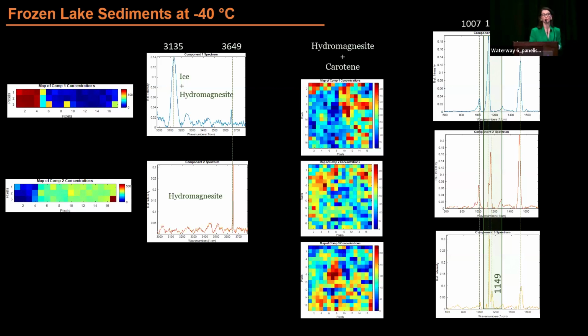And here, this was the first result to test the model with a much more complex organic sample with the hydromagnesite. What we have seen is that the water stretching region is perfectly located, with ice and hydromagnesite aggregated together. In the next slide, the carbonate region is much more complicated. Actually, it's a successful model, because the red dots correlate with the same model, components 1 and 3, showing that it's a mixture of the hydromagnesite and carotenoid, and they are very similar and follow each other. So that shows it's actually good.